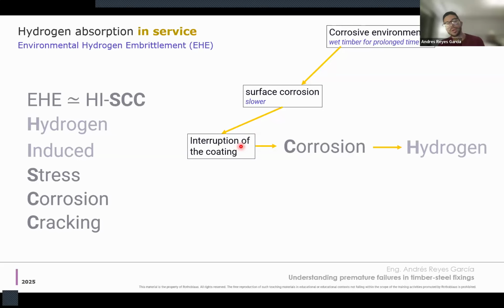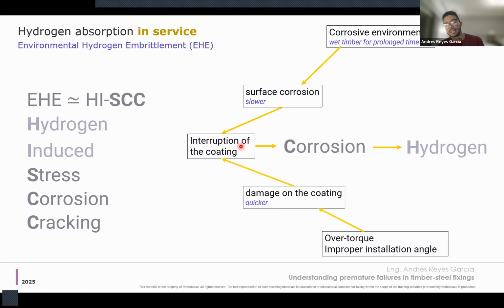Another way this interruption of the coating can happen is through some over torque or improper installation angle that will damage the coating, and this will happen quicker because the interruption of the coating from surface corrosion happens very slowly. But if it comes from damage of the coating, then that interruption can lead to corrosion and then hydrogen, and then we will have the phenomenon that we saw before.